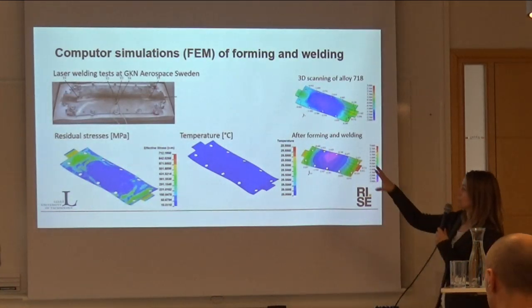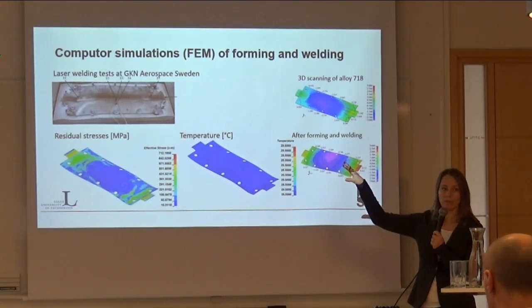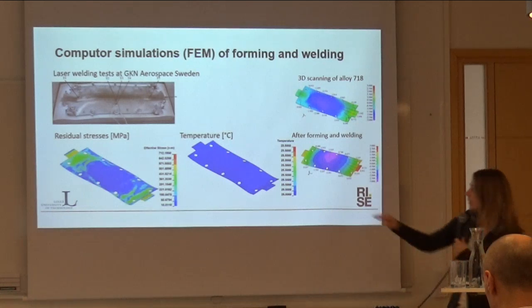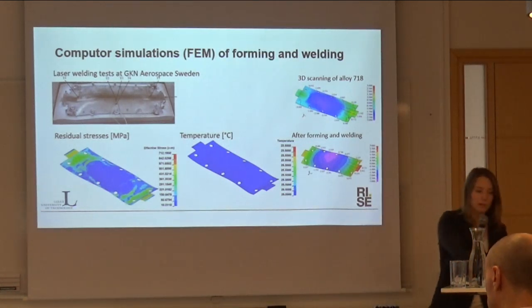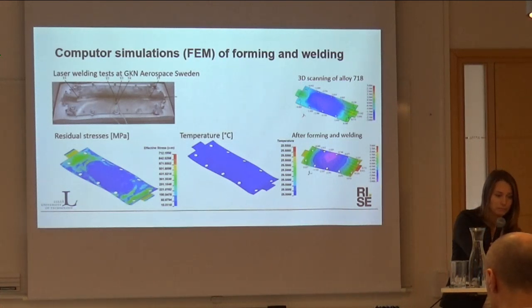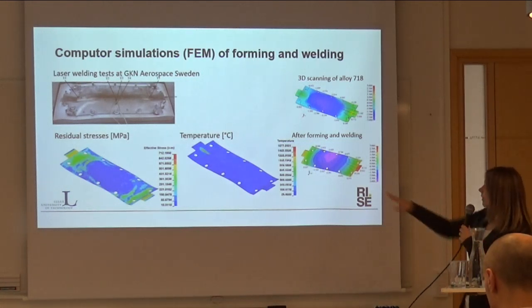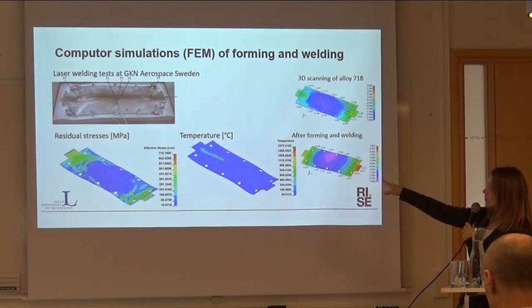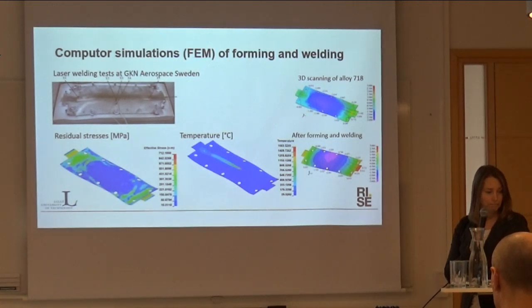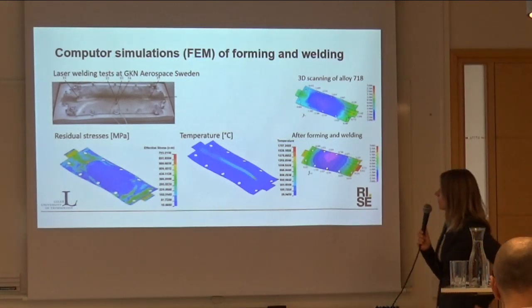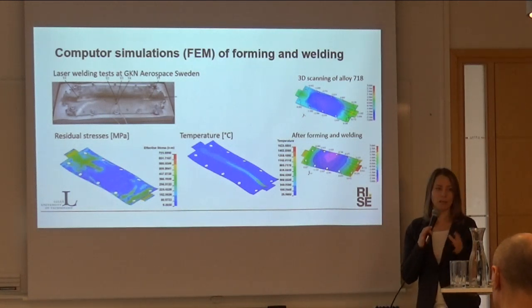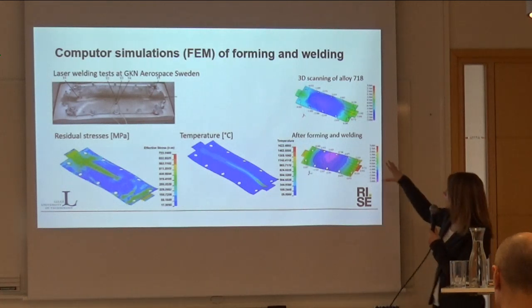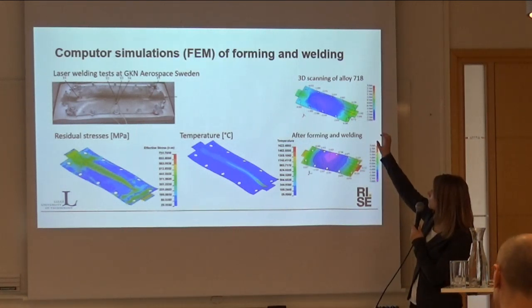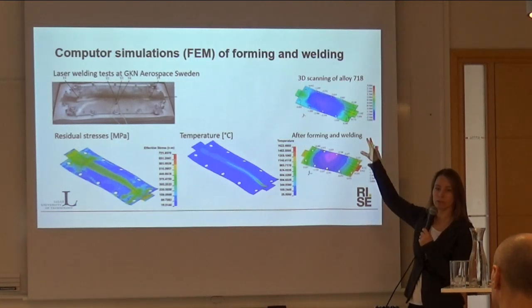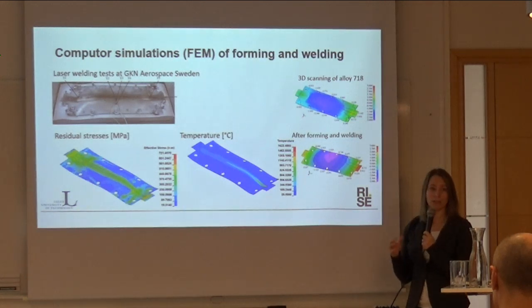We also extracted a part from the formed geometry and performed welding tests. So here we have the residual stress state after forming, and then we did simulations of the welding procedure. Here you can see the temperature increasing as the torch moves over the part. And here you can see how the residual stress state changes, and of course it introduces shape deformations in the part. So we have worked with both simulations but also produced forming tools, welding fixtures, and measured the shape deviation compared with simulations.